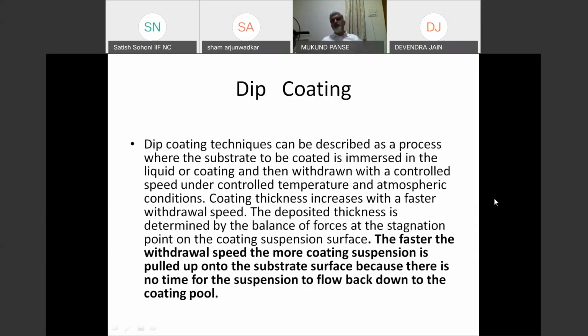The third process is dip coating. Dip coating is mainly used for cores. That also when the cores are small and large production runs are there, so you can standardize the coating thickness which you get. If you withdraw it fast, there is no sufficient time for the paint to drop back into the tank and the thickness will be more. Also, the faster the withdrawal speed, the more coating suspension is pulled onto the substrate, because there is no time for suspension to flow back. You should standardize the timing. If it is completely mechanized, it is better. This can be done only where large runs of cores and molds are used.